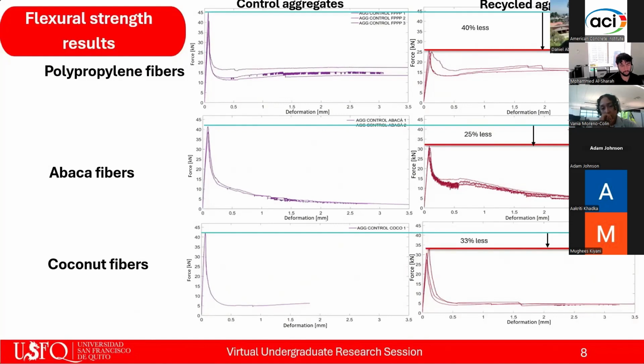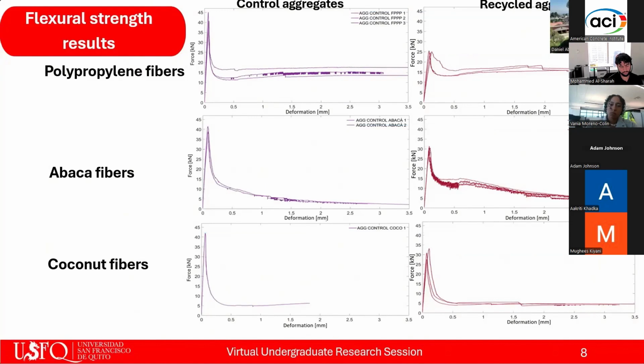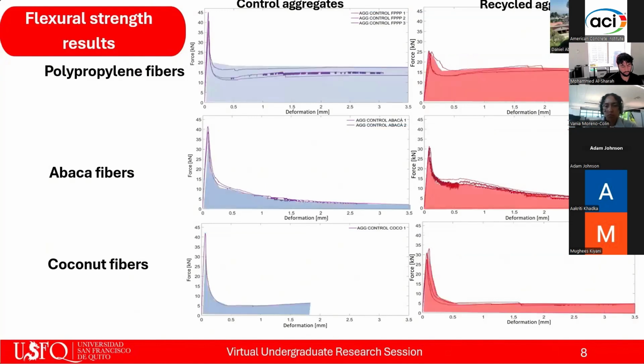Analyzing post-peak behavior, all beams except those with abaca fibers maintain relatively stable strength after the maximum load. Beams with polypropylene fibers resisted on average 15 kilonewtons after the peak, those with abaca fibers about half of that, and those with coconut fibers roughly 1/3. Toughness, measured as the area under the load-displacement curve, varied notably with fiber type. Polypropylene fibers achieved the highest energy absorption, around 54 joules. Abaca fibers reached about half that value, while coconut fibers showed roughly 1/4. These differences reflect the higher energy absorption capacity of synthetic fibers compared to natural ones.